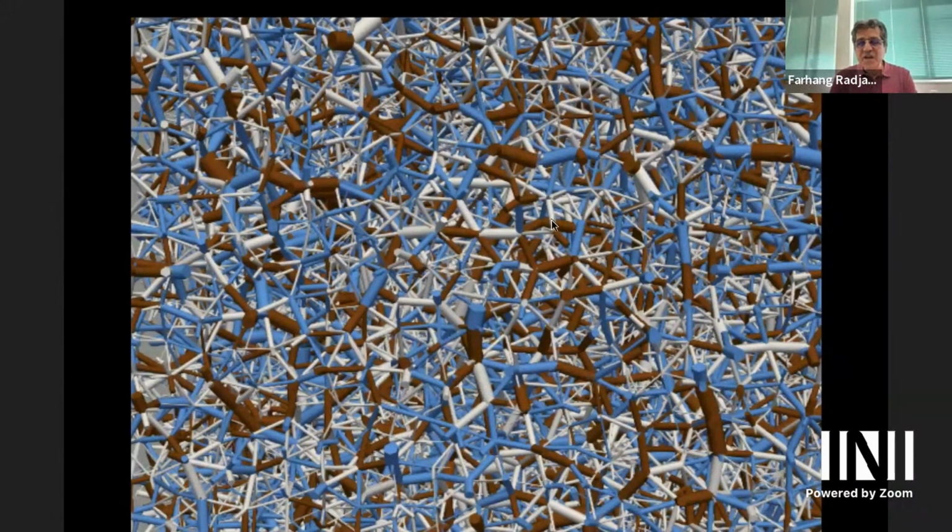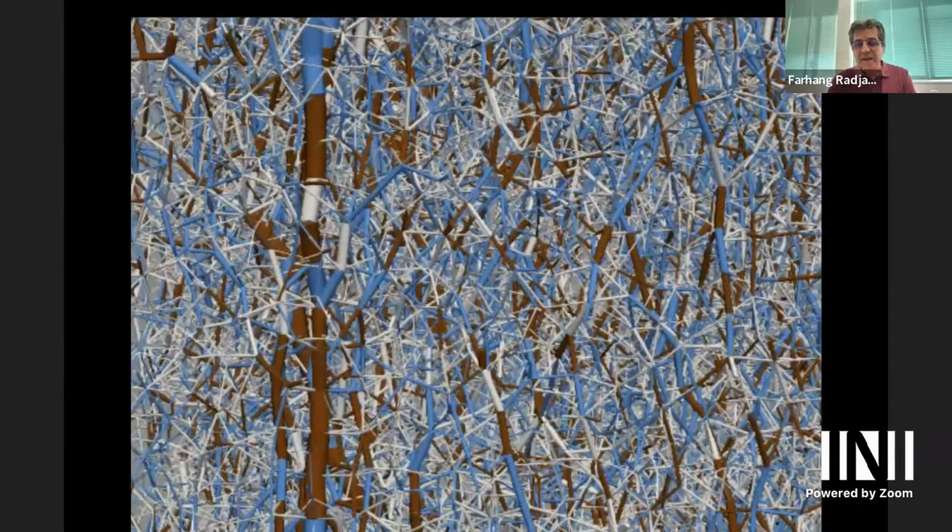And you can see that initially, because it's isotropic, we have a kind of mixture of all of them, although the percentages are different. We have 14% of contacts which are triple only. And here is at the peak, slightly before the peak stress, and you see it's organized. We see the anisotropy of the packing, and we see that most of these strong force chains here, the thickness is proportional to the force, are oriented along the axis of compression.